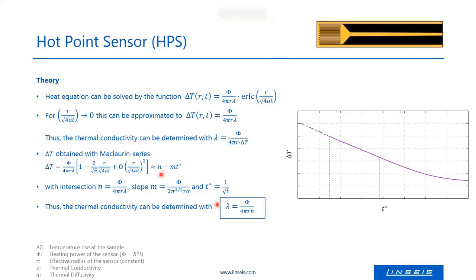And by theory, from the intercept of this curve with the y-axis, you get a delta t. And with that delta t, this is the intercept. This delta t is inverse proportional to lambda. So if you have that, and if you know the heating energy, then you can calculate lambda from this intercept. The slope of that curve depends on the thermal diffusivity alpha. So if you calculate the slope, you can calculate also alpha, the thermal diffusivity.